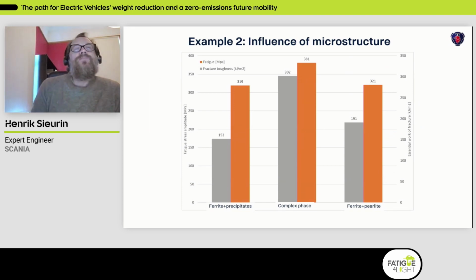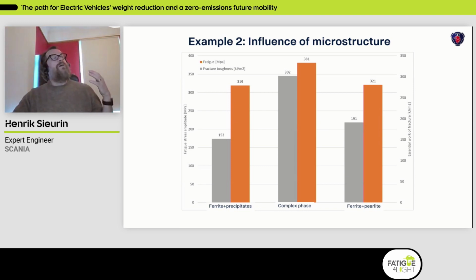So one reason for this, or we try to understand why, we did fracture toughness testing performed at EURECAT with this essential work of fracture method. And as you can see, this complex phase steel had almost a doubled fracture toughness compared to the other materials. So that indicates a better or a lower crack propagation rate. So here we come into this notch sensitivity, because in a punched hole, you always have crack initiation. You already have micro cracks. So it's really about the crack propagation.